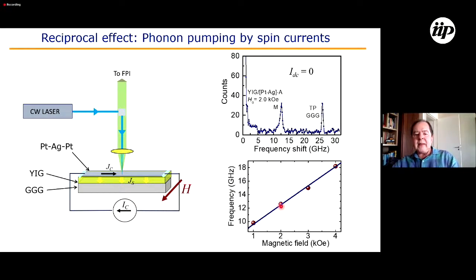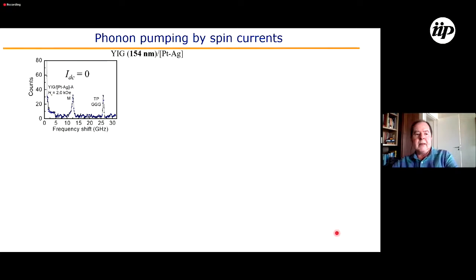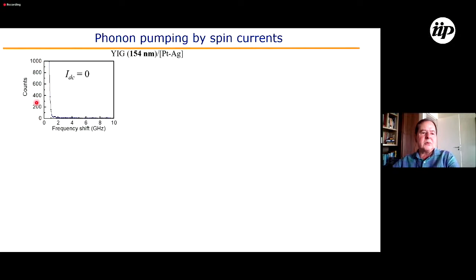If we vary the applied magnetic field, the whole thing is in a magnetic field, the frequency of the magnon increases, as it should. It goes from 10 to 18 gigahertz with a field of 4 kilo-oersted. So here is the spectrum again. I'm going to change the scale here from 0 to 80 counts to 0 to 1,000 counts with no DC current.